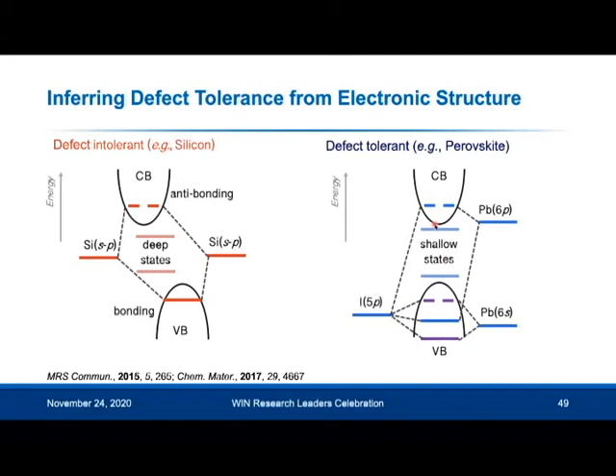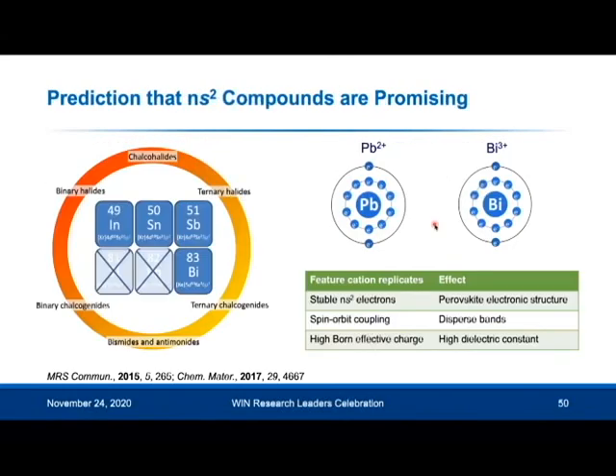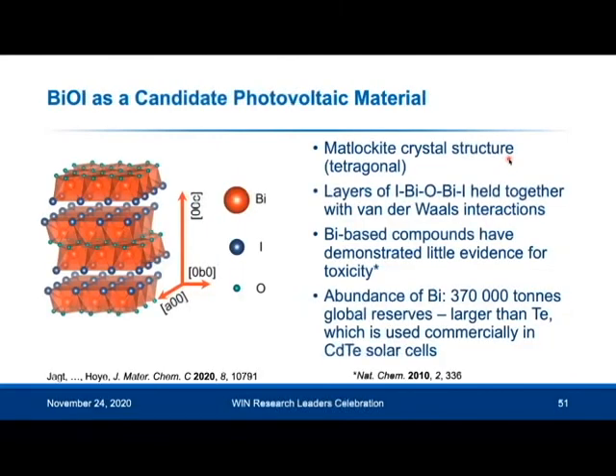So we hypothesized that we could find materials with this defect tolerance if we could find materials with a very similar electronic structure. And we looked towards materials with partially oxidized p-block cations, such as bismuth. So bismuth forms a stable 3+ oxidation state, which means that it then has the same electron configuration as lead does. And one of the materials we looked at is bismuth oxyiodide.